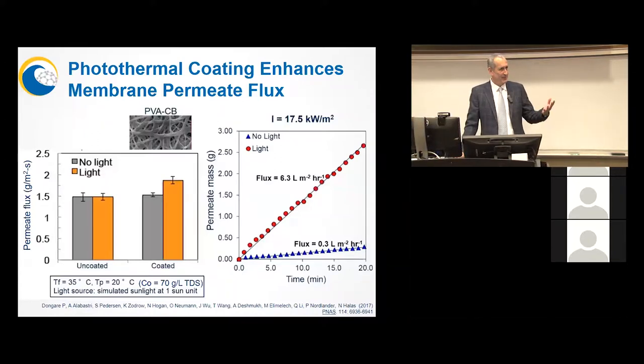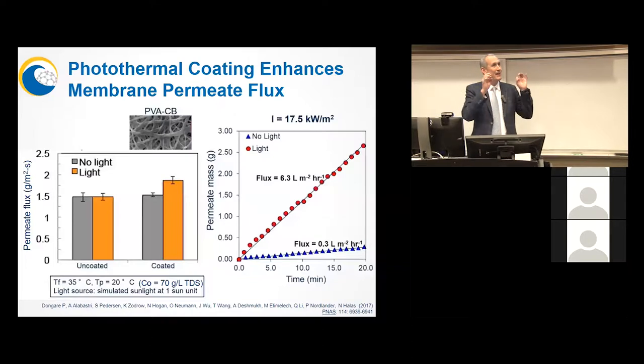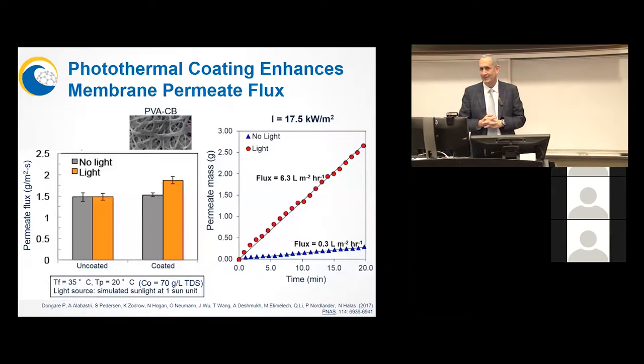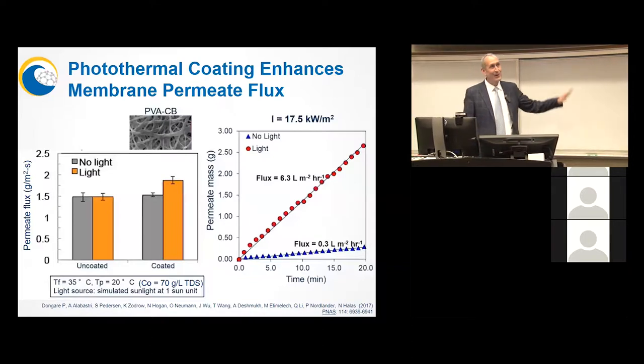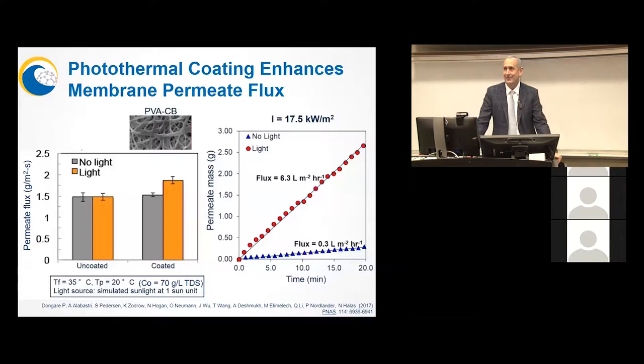Peter Nordlander has been doing some Monte Carlo modeling, and he's finding that we can even improve on this significantly by choosing carefully the interparticle distance and the thickness of the cover layer, and by using micro lenses to focus the light better. But what is important here is that we already have decreased the cost of desalination by 1/2 in these small units. Because remember, 1/2 of the cost was electrical energy, and here we're using a free source, which is sunlight.